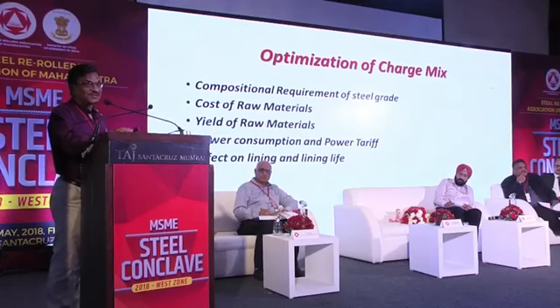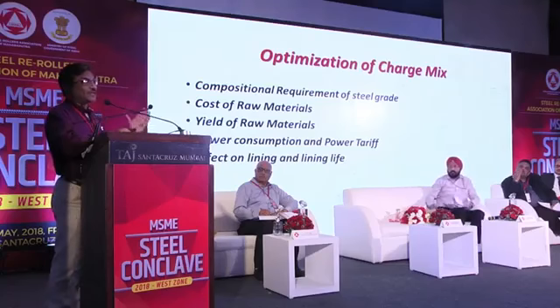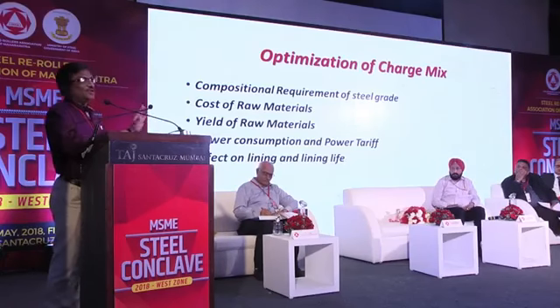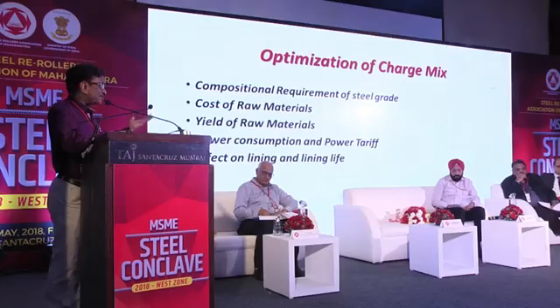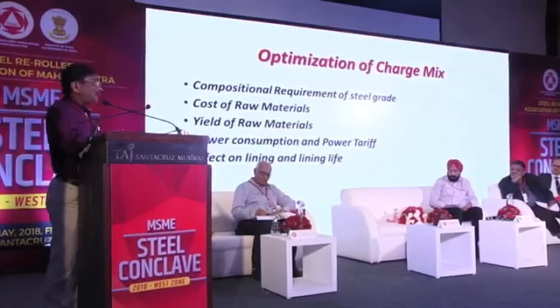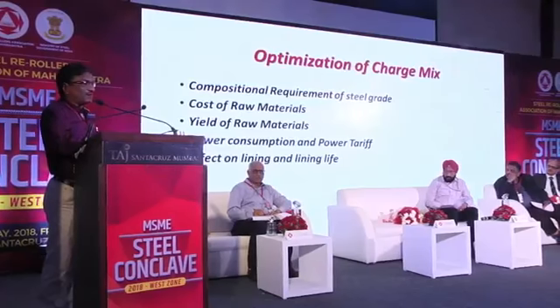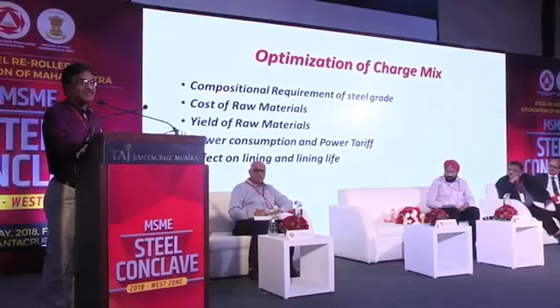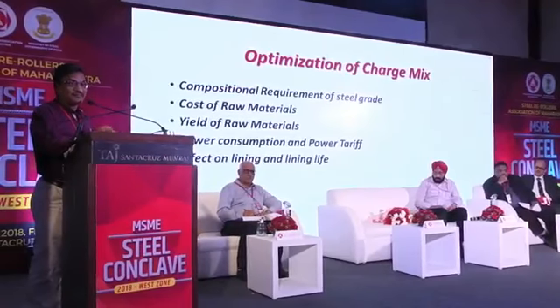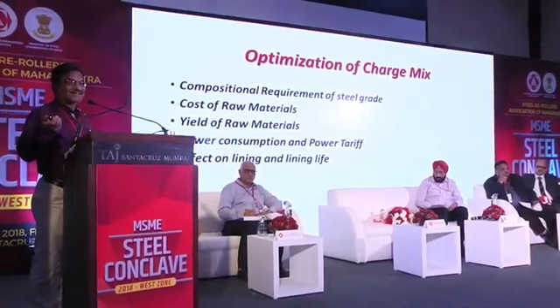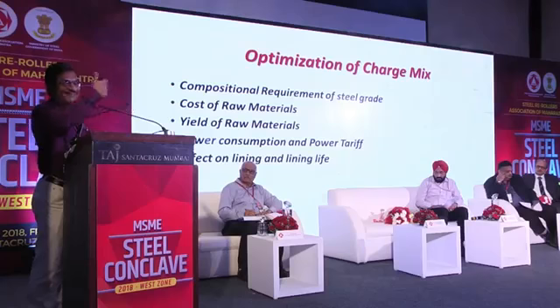Scrap is always costlier than the sponge iron, but on the other hand, sponge iron has a lower yield. Not only lower yield, it has a bad effect on other process parameters also. Cheaper on the one hand, but it has some negative impacts on my process. Yield of the raw materials, power consumption and power tariff. At some place, maybe where the power is cheap, I can afford to use more of sponge iron rather than the scrap. But where the scrap is cheap, say in this region, where import of scrap may be available at a cheaper rate.